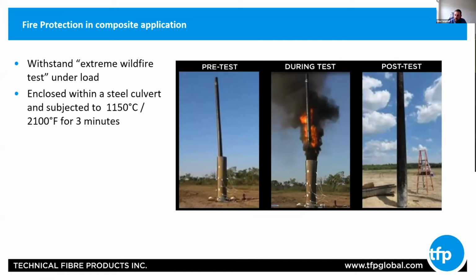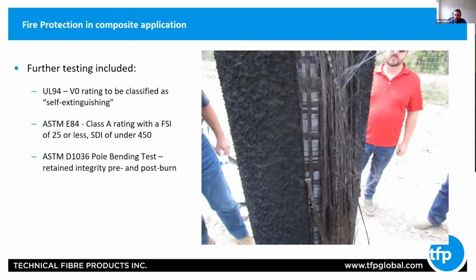This is a commercial project where Technofire was added on the outside layer of a composite power transmission pole. This test was designed to replicate a forest fire event while under load. The fire burned at 1150 C for 3 minutes, and the pole with Technofire was able to handle it. In this picture, you can see where the Technofire was included and was not included. There was a dramatic difference. The structural fibers were damaged where the Technofire was not included.